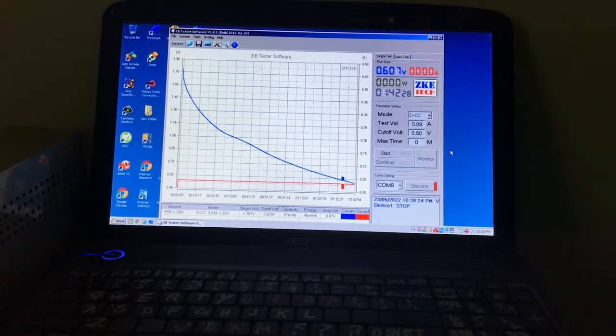Fourth run after a 2-hour charge, 30 milliamp load this time because it was getting late. 51 milliamp hours, 45 milliwatt hours. Average voltage 0.87, down by 0.01 of a volt, but a higher load.